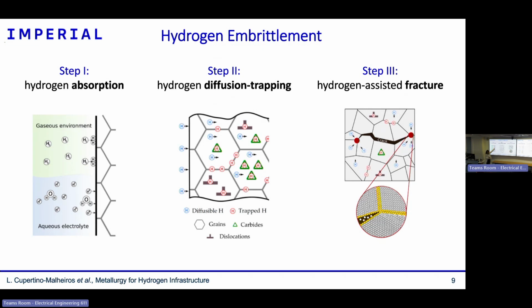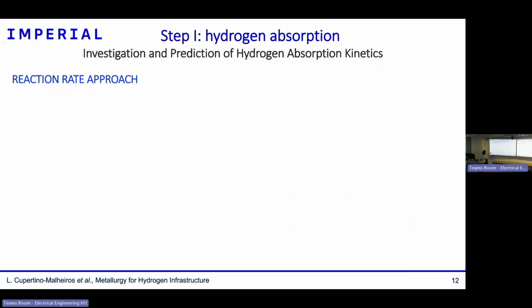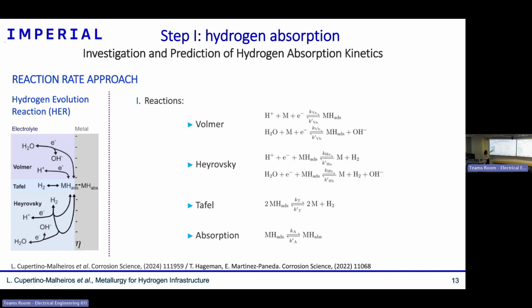So it's the hydrogen atom. In the electrolyte, the same thing, it's always the hydrogen atom. In that case, hydrogen comes due to the reduction of either a proton or water in the electrolyte. And then you get these sorts of reactions. But again, you have this adsorbed hydrogen atom at the surface, and part of it can enter the surface and get absorbed, so diffuse through the interstitial sites. So in any case, it is the hydrogen atom that can move inside of the metal.